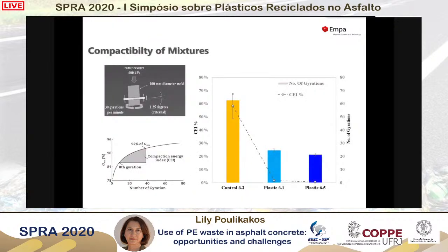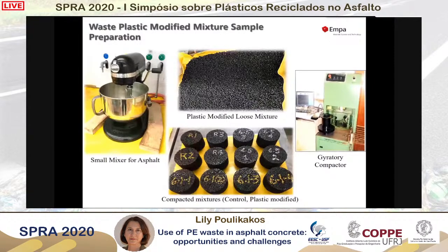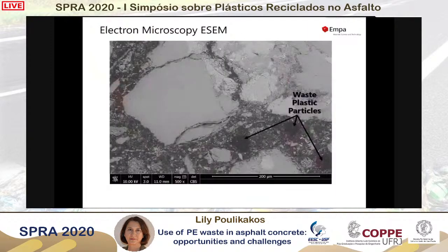So we used the gyratory compactor to compact these mixtures, and what was striking was the ease of compaction. So adding just that small amount of polyethylene made a big difference in terms of compaction. So there were fewer gyrations needed and less compaction energy, as you see here for both polyethylene modified mixtures that we looked at. We used a small mixer, as we could not produce a large amount of shredded PE waste to do our experiments. Once the mixtures were compacted, we cut, impregnated and polished them so that we could look at them with the electron microscope.